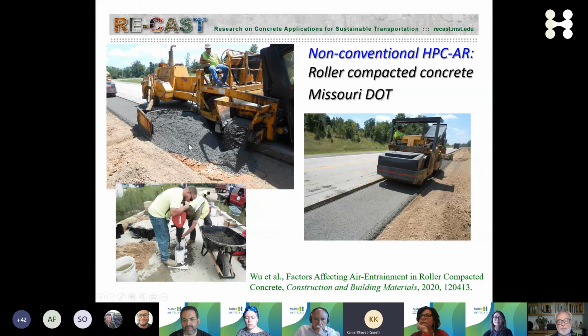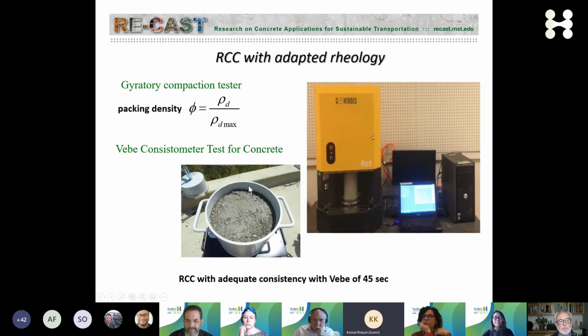And this is roller compacted concrete, so it's not a conventional high performance concrete with adapted rheology, but believe it or not, the design of this RCC is very much affected by the rheology of this zero slump concrete. This was a field demonstration or field trial with Missouri DOT using different types of RCC, but these RCCs were designed through a special approach for packing density of the aggregate, special selection of the binder, but also with a rheometer, if you would, for very low slump concrete. And this is a gyratory compaction tester. It was compared to the Vebe consistometer and found that if you reduce the Vebe time to about 45 seconds, it gives you much better productivity and consolidation effort.